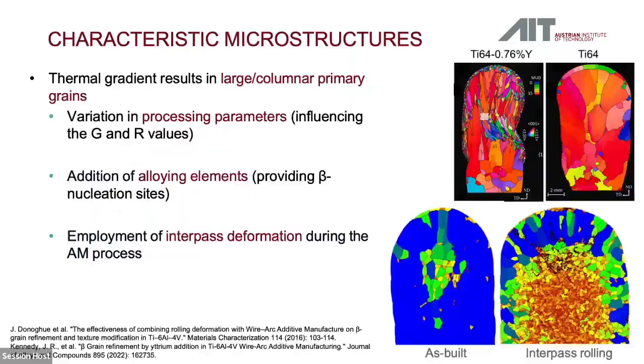Of course, the process has some shortcomings, and they are mainly found in the microstructure. Best seen on the right-hand side here. This is standard titanium 6-4 after the additive process, with no heat treatment and no additional elements included. You have a very coarse-grained microstructure that typically is also textured and results in anisotropic mechanical properties.